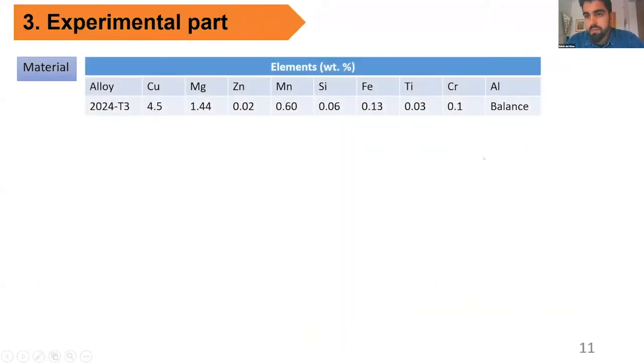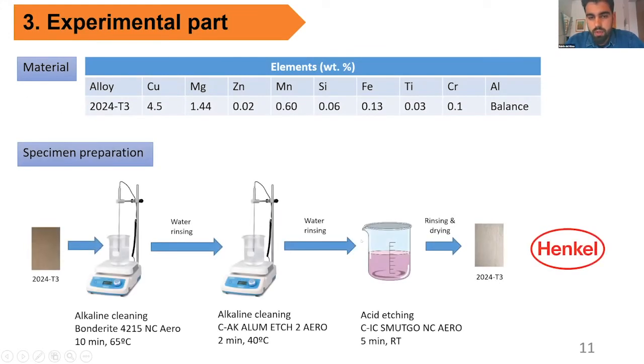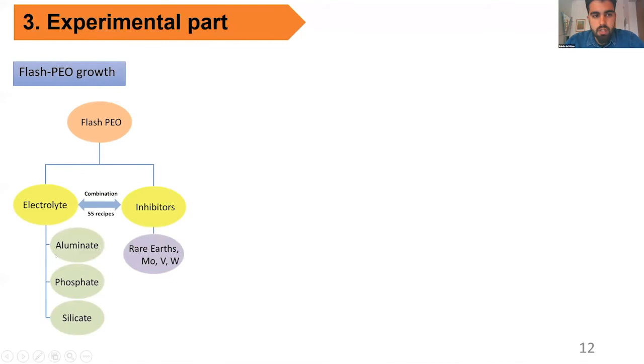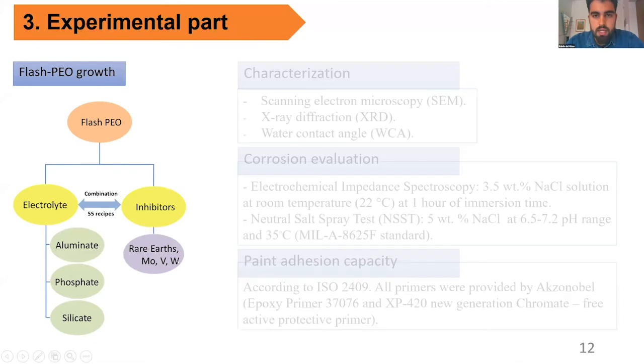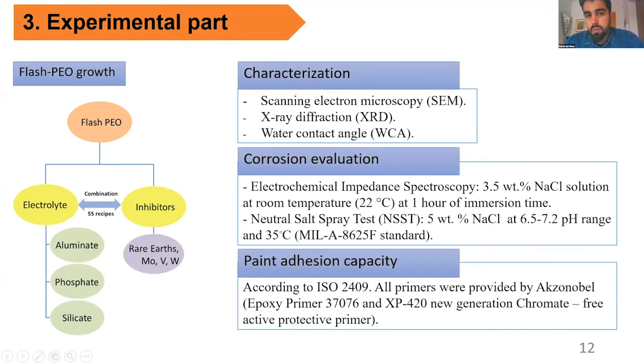Regarding the experimental part, our base material is 2024-T3 aluminum alloy. We performed the specimen preparation according to the industrial procedure prescribed by the Henkel company. We studied the formation of flash PEO coatings using several types of electrolytes and different corrosion inhibitors, and studied these coatings by characterization techniques like scanning electron microscopy, X-ray diffraction, and water contact angle. The corrosion evaluation was performed by electrochemical impedance spectroscopy and neutral salt spray test according to this aircraft standard. And paint adhesion capacity was evaluated according to this standard and with paints provided by AkzoNobel.